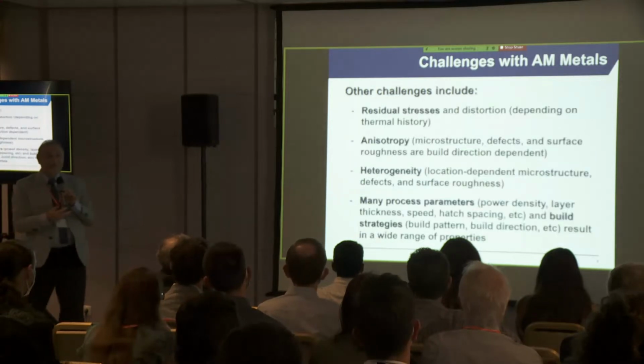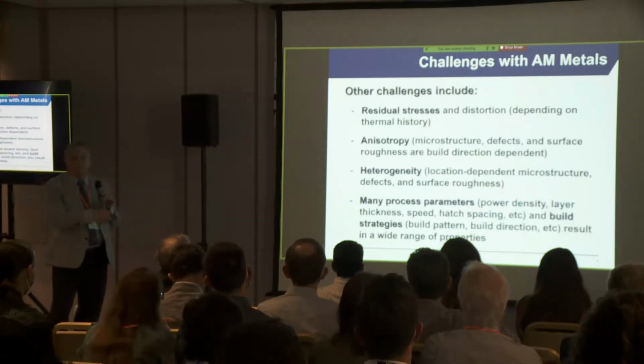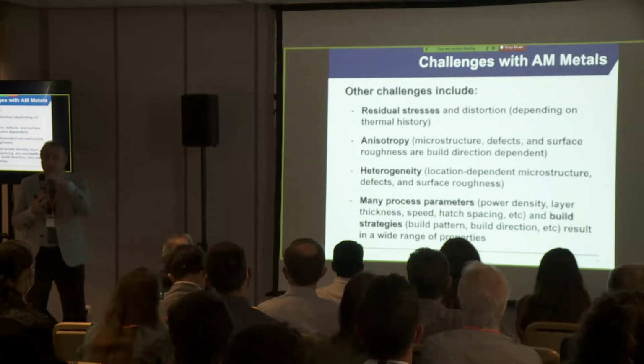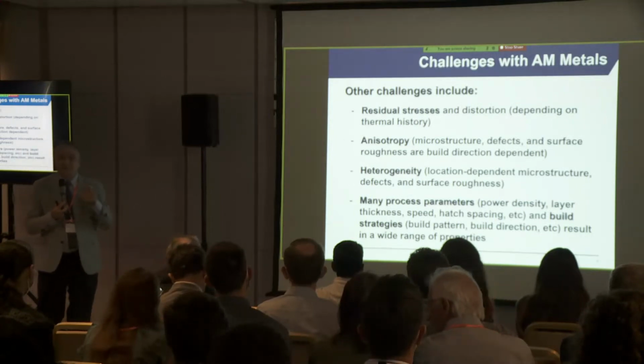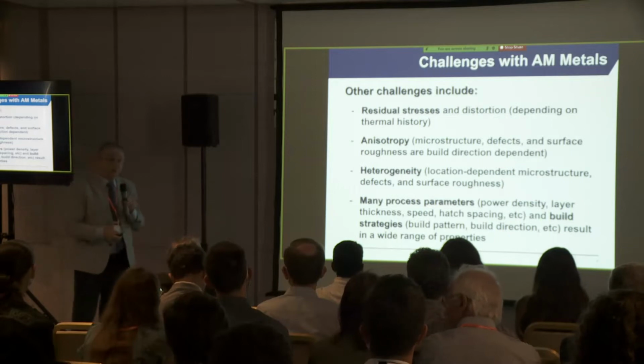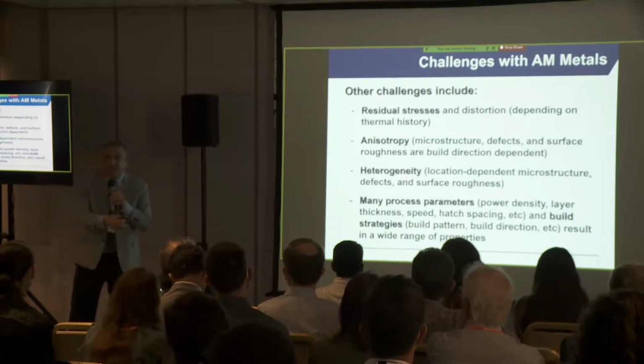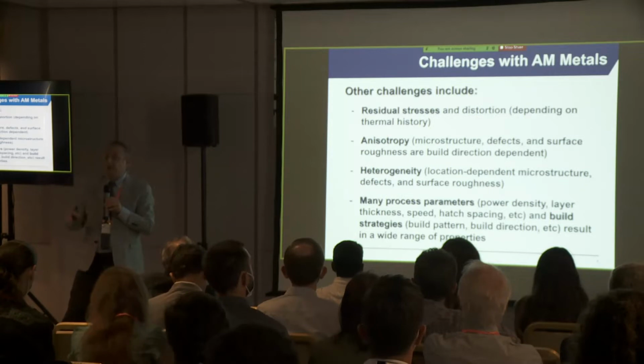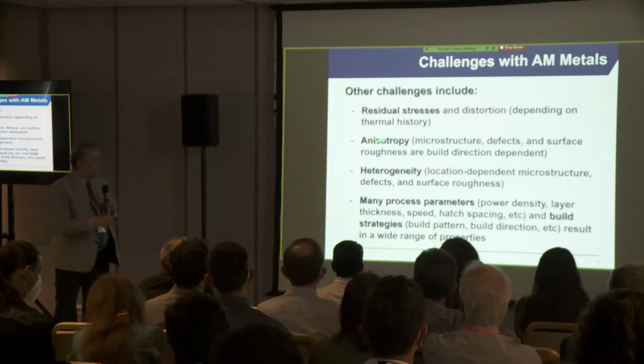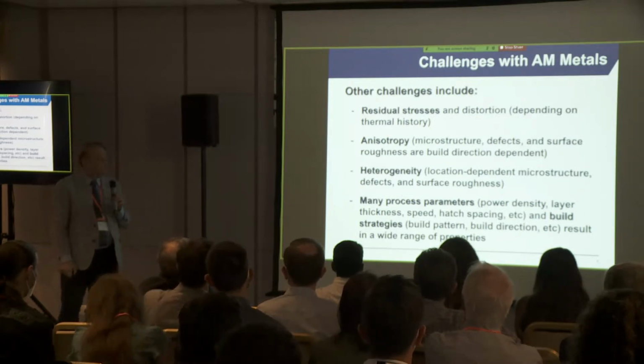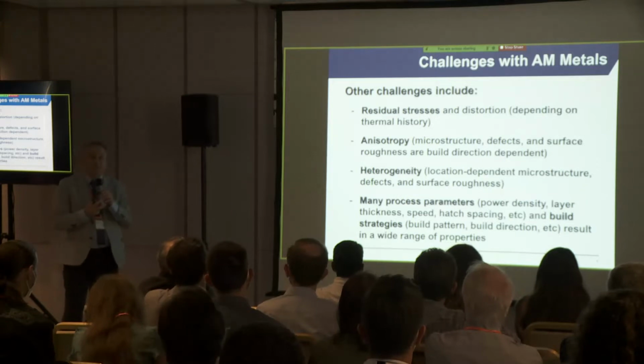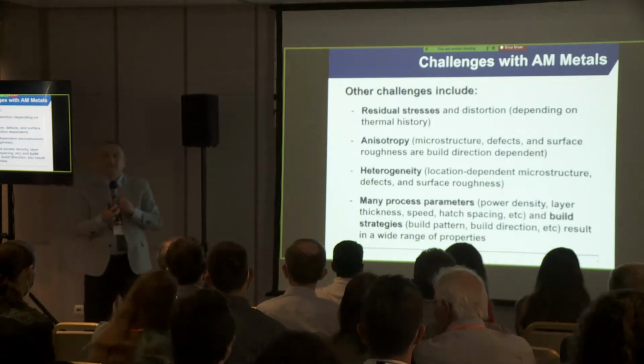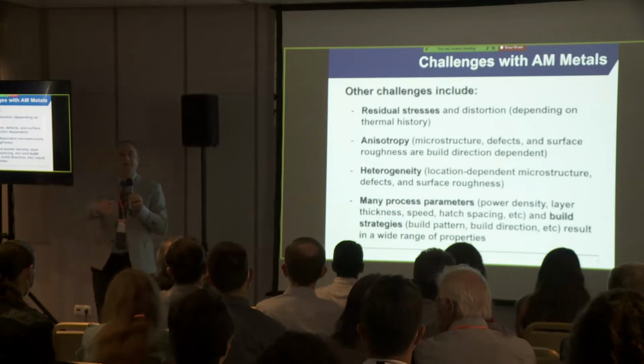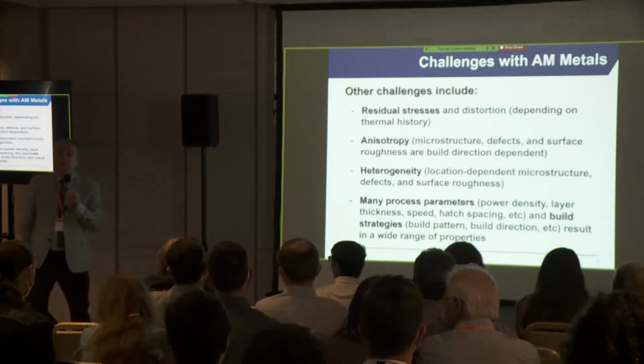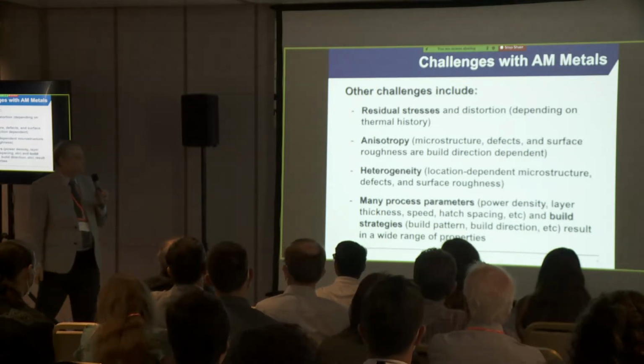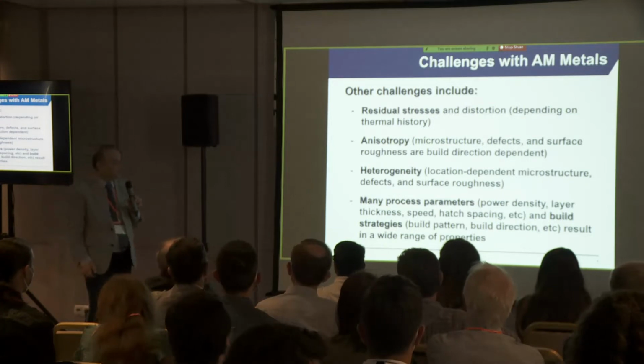There are other challenges with additive manufacturing, including residual stresses, because different parts of the component goes through different thermal histories. So residual stresses not only are significant, but again, they are very variable throughout a single part. Anisotropy is oftentimes an issue, and heterogeneity. Different locations of a given part can have different properties, different microstructures, different defect populations, and so on.